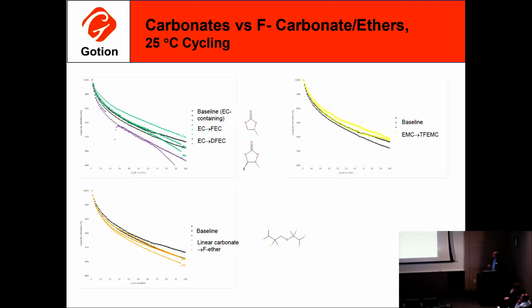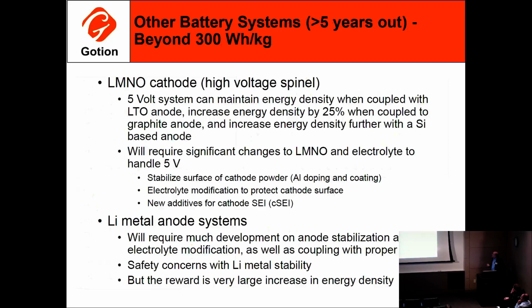But you can see that in the long run, as far as cycle life, if you take a baseline here and you add some fluorinated additives, you can increase the capacity, long-term capacity, pretty significantly. So we know in this particular case with silicon, fluorine is good. And there's a lot of development on additives to find the right fluorinated additive. And last slide. So this is how do we get past, once we get to 300, how do we get past that? What's next after that?